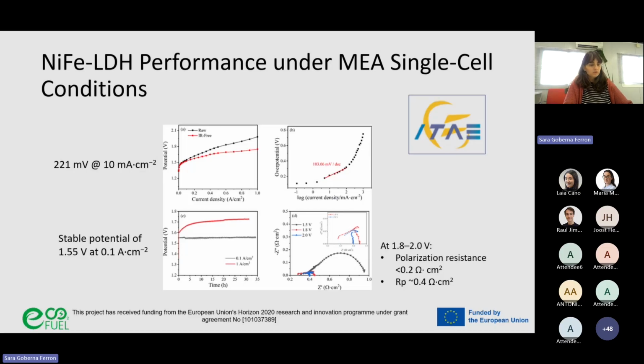Now, here in the bottom right, we have some electrochemical impedance spectroscopy data. So basically, what we can see is that the nickel iron LDH catalyst reaches operation voltages between 1.8 and 2 volts. We can see here in red and blue that the semicircle becomes much smaller, showing a clear reduction in the polarization and the low frequency resistance. So that means that the oxygen evolution reaction becomes much more efficient at these voltages.